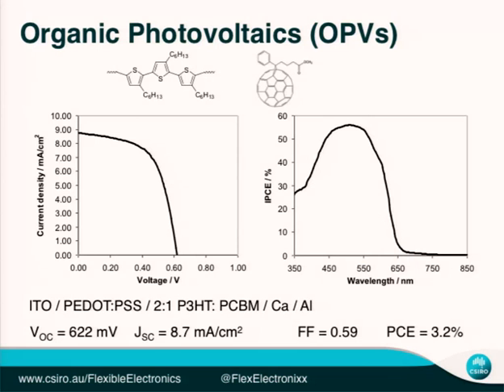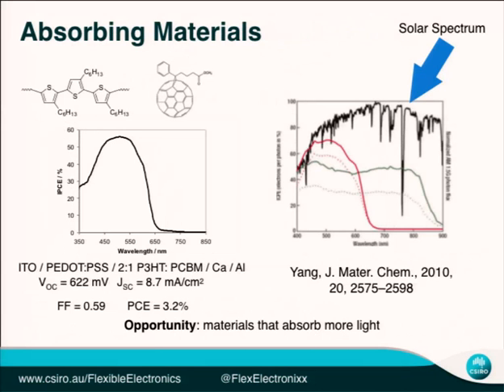Now, what's really, I guess, exciting about organics is that we can tune that property, that absorbance property. So the chart from the previous slides is reproduced here, where with P3HT we're absorbing out to 650, but shown over here is the solar spectrum, and you can see there's a lot of energy out here, out in the IR, that we're not collecting. So we can use different organic semiconductors, as shown here, that actually absorb light more out there. And this is a really different situation with silicon, because silicon's got a fixed band gap, and you can't do anything to change that. So the amount of light it absorbs is fixed. With organics, we can tune the energy levels such that they can absorb different amounts of light, and the possibilities are really endless. We've got the whole periodic table available to us.